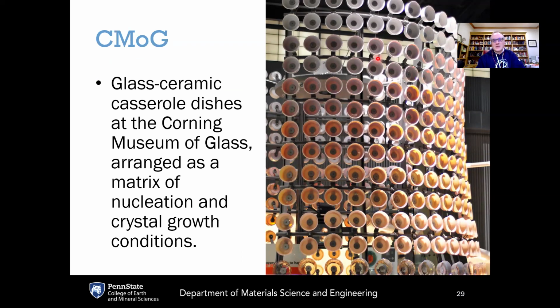It's been very successful. And in fact, if you go to the Corning Museum of Glass, CMOG, you can see some of this Corningware that Dr. Stookey had invented, which is a glass ceramic cookware. And what you can see is a function of the crystal growth time, where this is a low amount of crystal growth. This gives you the transparent cookware that has smaller crystals. This is like the Corning Visions cookware.